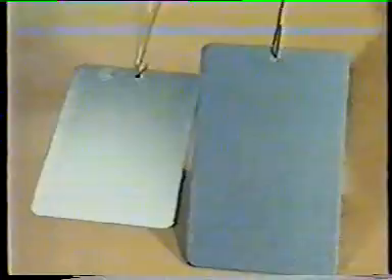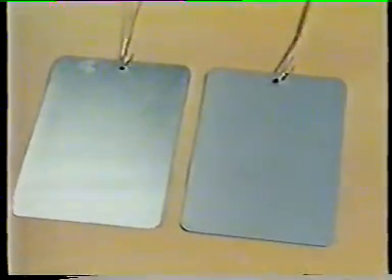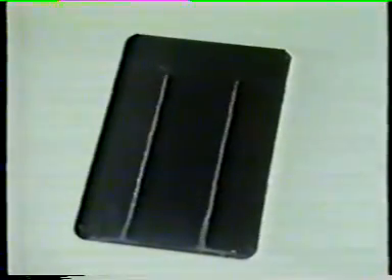If we compare this with a steel sample that hasn't been coated, you can just see the difference. If we take a much closer look at the coating, you see phosphate crystals. This coating not only provides a key for the paint, it also gives added protection to the steel. Here's the result after painting and testing. This time the paint has adhered to the surface and the rust hasn't got underneath.